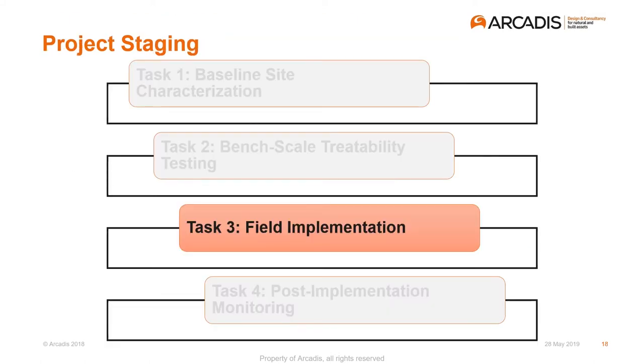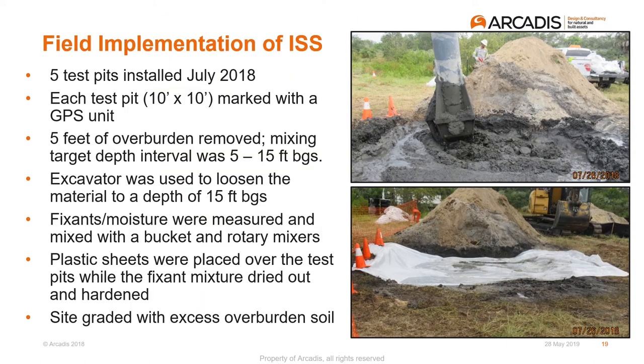So with that, we took this to the field, and the field implementation was what you would expect. A lot of dirt, a lot of mixing, a lot of cursing, a lot of yelling. The 5 test pits were mixed in July of 2018. We did 10 by 10 by 10 pits.